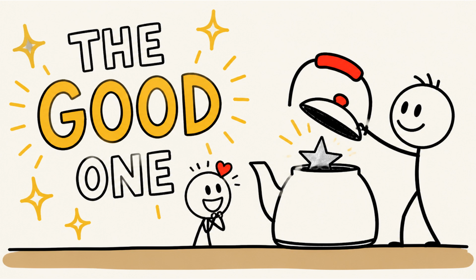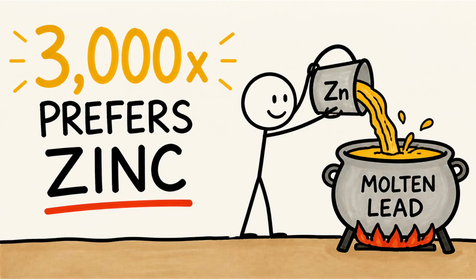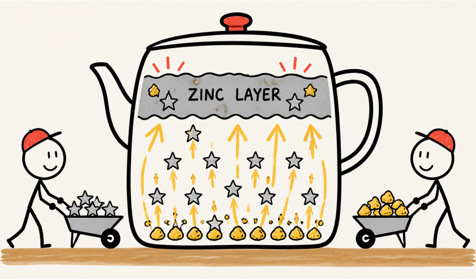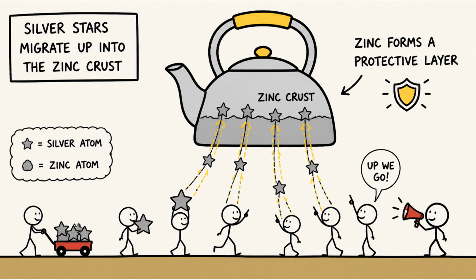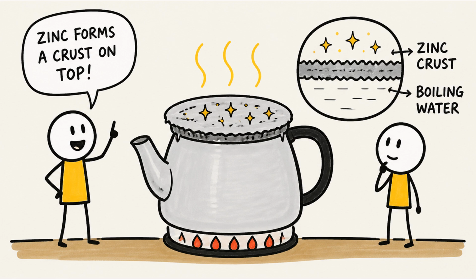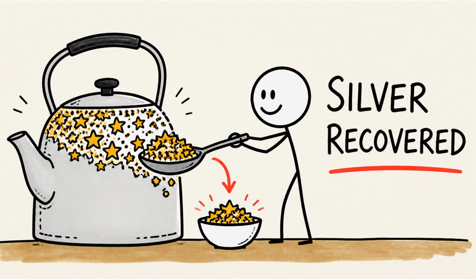And now comes the strange one, the good one. Remember I said there was silver hiding in there? Here's how they get it out. They pour zinc into the molten lead. And it turns out that silver is about 3,000 times more comfortable dissolved in zinc than in lead. So the silver, and any gold, abandons the lead entirely and rushes into the zinc, which floats up on top as a separate silvery crust. You skim that crust off, and you've just pulled precious metal out of a vat of lead.